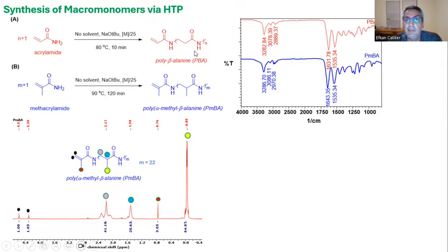So after polymerization, we got FTIR spectra, which both showed us secondary amide bonds of amide carbonyl and NH stretching bonds. To make sure, we obtained NMR spectra, which has vinyl protons of methacrylamide groups, also showing the formation of macromonomer at the end of the polymerization.